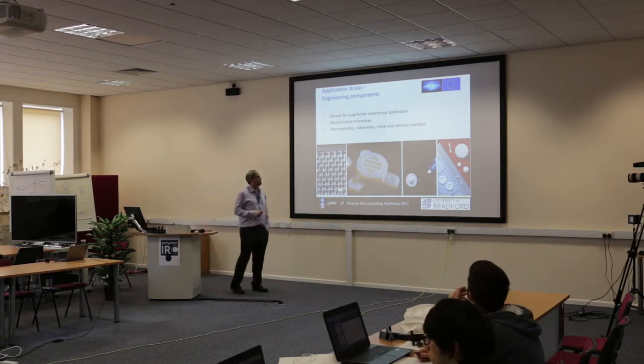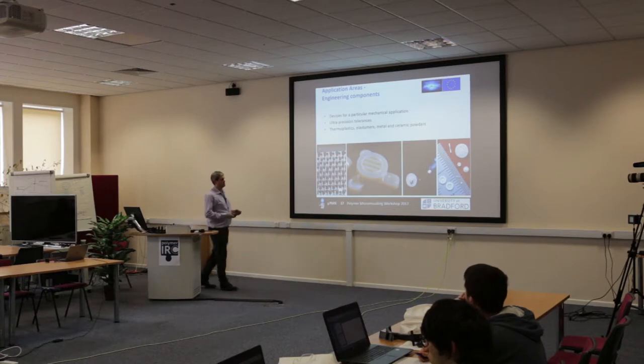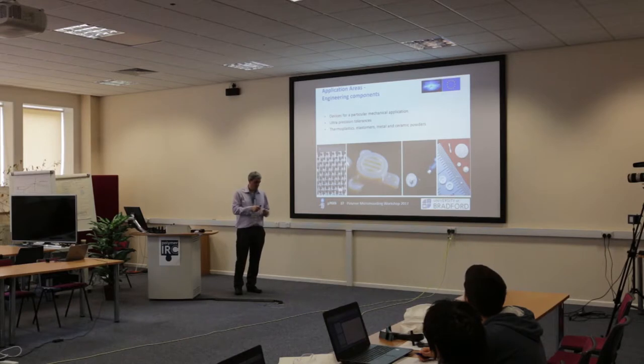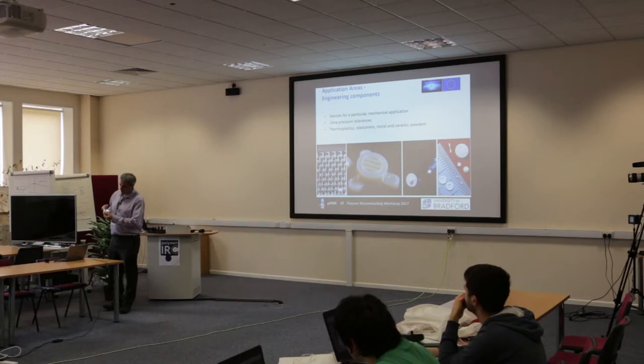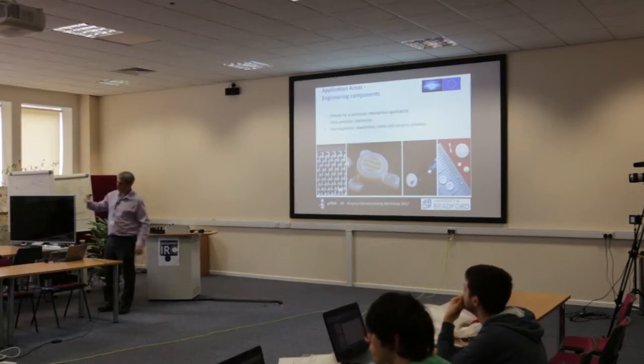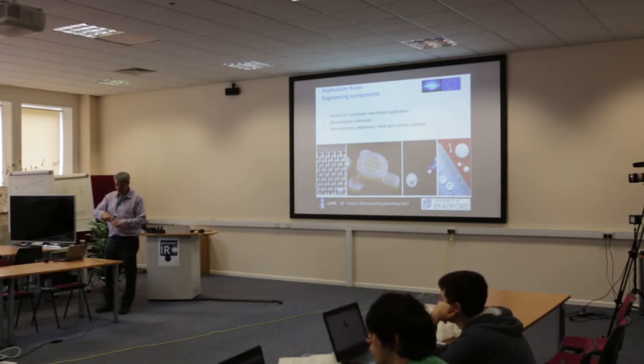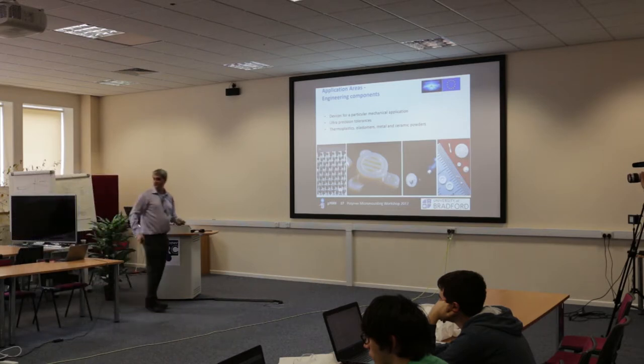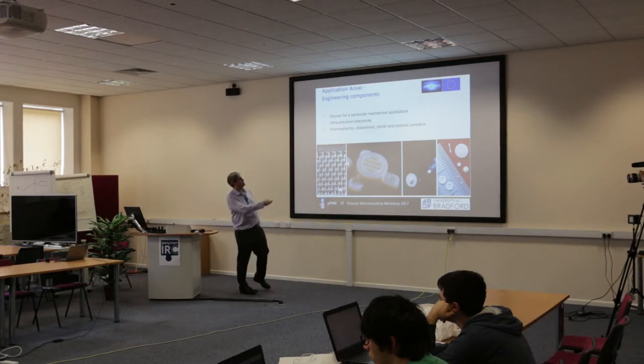Once we have these technologies, we can apply them across a range of application areas. The first is engineering components — parts used for their mechanical or thermal behavior. One nice example is a PEEK bobbin requiring tolerances of just under 10 microns for the gaps between fins. It acts as an inductive sensor for measuring electroplating coating thickness, with copper wire wound around it — so we must ensure no stress concentrators, split lines, or edges that could break the copper wire. Mechanical components such as polymer watch gears are another example.